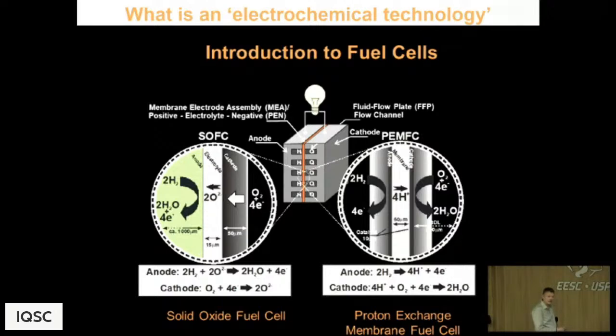And the combination of voltage and current, of course, is power. So we produce power as we pass increasing amounts of current. But the efficiency of the device depends on the voltage. Right? So the maximum efficiency of an electrochemical device, in a fuel cell context, the theoretical efficiency, is the Gibbs energy over the enthalpy of that reaction.